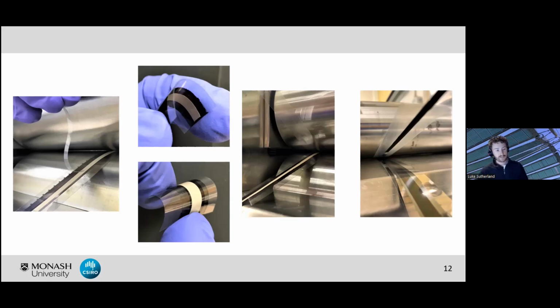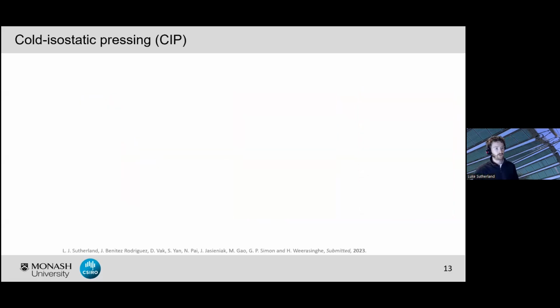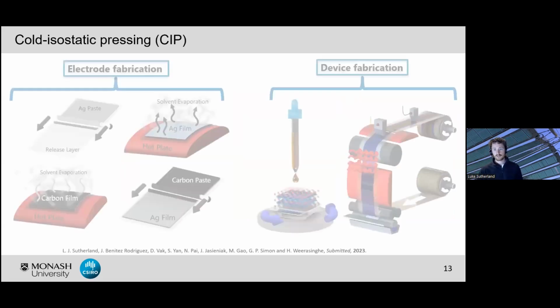And so we investigated a range of other mechanical pressing techniques in order to try and really boost the versatility of this dry press deposition using our bi-layered coated carbon and silver electrode. And we came out the other end investigating cold isostatic pressing. Cold isostatic pressing is typically used for the fabrication of metal alloy rods from base metal powders, where you can apply extremely high but uniformly distributed pressure within your CIP chamber. And as we'll see, it's actually pretty good for the fabrication of perovskite solar cells as well.